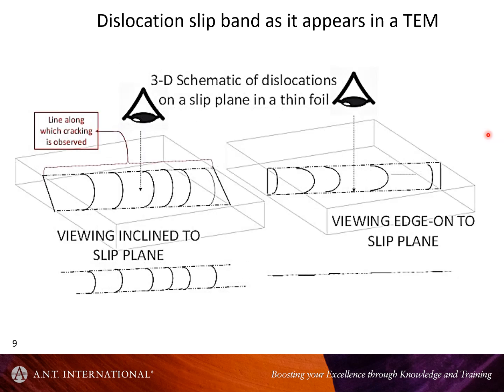Here's another couple of schematics just to show how one would view a slice through a slip plane and how it would appear in the microscope. And if you really wanted to verify that you have slip on one plane, you'd have to tilt the slip plane to the edge-on configuration, in which case you'd just see little lines like this.